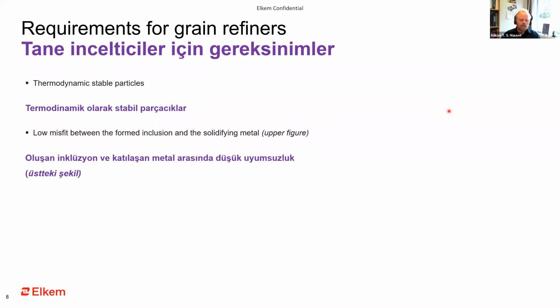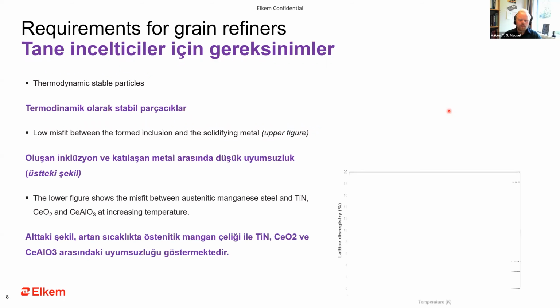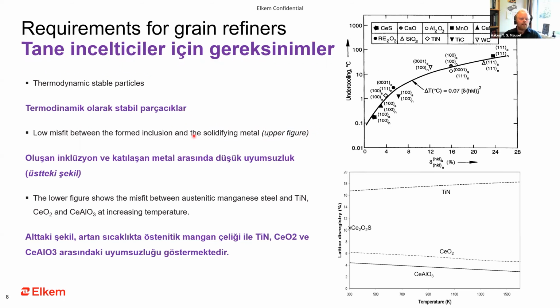But what are the requirements for a grain refiner? You need to have thermodynamic stable particles. It doesn't help you if your particle dissolves in the steel. It needs to be a thermodynamic stable solid particle. And then there needs to be a low misfit between the formed inclusion and the solidifying metal. And this can perhaps be a bit difficult to interpret.